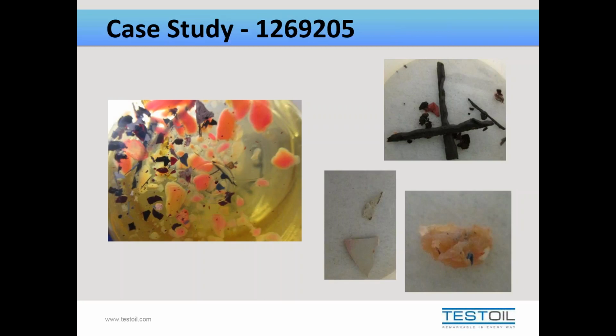So we recommended materials identification analysis so that we could really dig into all the multiple contaminants that were present there. So we used elemental spectroscopy and viscosity to help characterize the oil itself to ensure that the correct oil was being used in the system. We found that it was. And then we started to identify the 3 different types of contaminants that we had here.